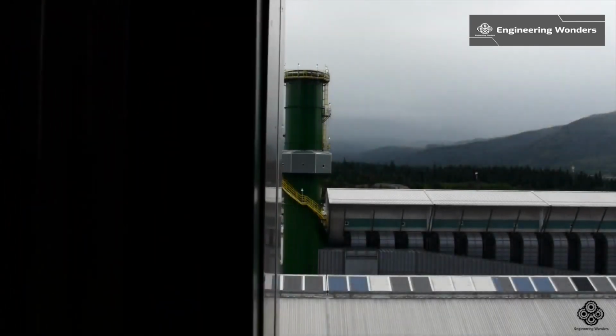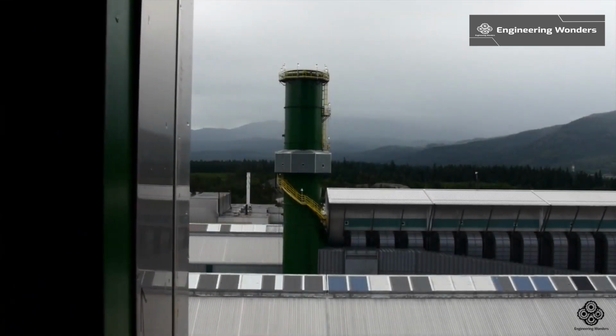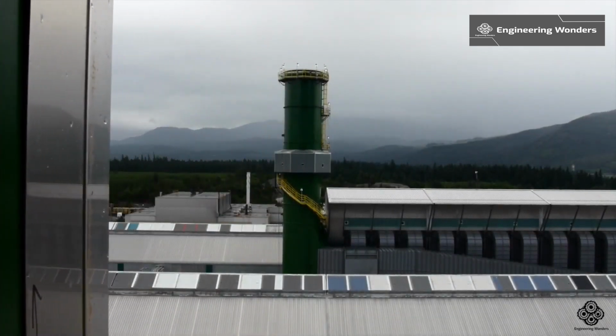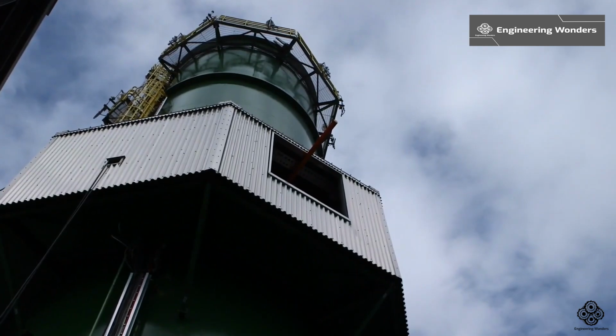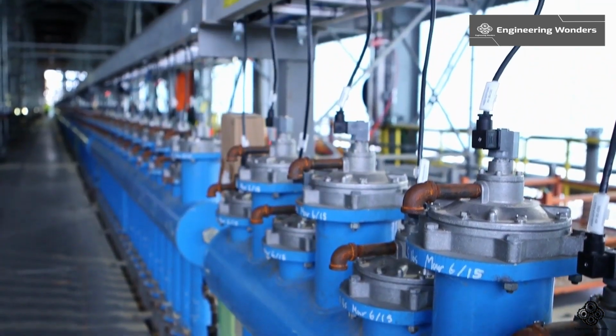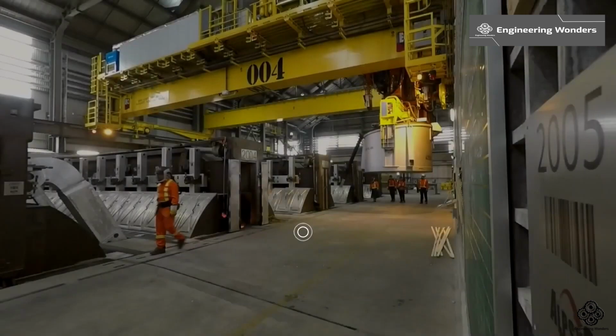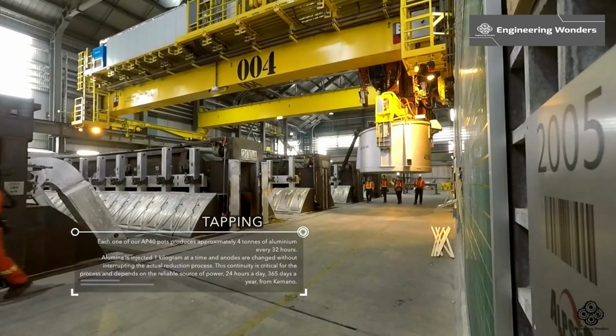temperatures of up to 1,200 degrees Celsius for about 20 days. Over 600 pre-baked anodes are produced daily to ensure a continuous supply for the smelting operation. The anodes are transported to the pot rooms where they are installed in the pots.